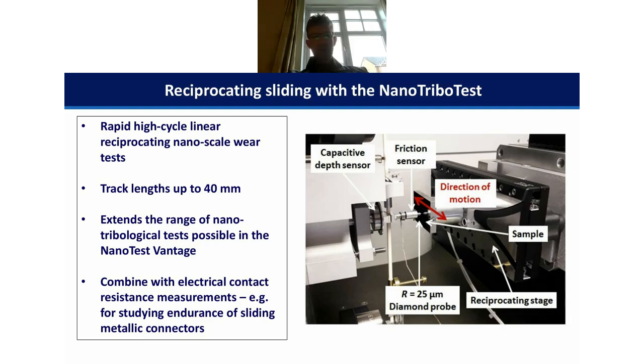So we've looked a little bit further at these sliding contacts with our new NanoTribo test. Here we have an additional stage, which we control within the NanoTest software. And it rapidly goes backwards and forwards here. This allows us to perform very high cycle tests, very long track sliding distances, and we can even combine with electrical contact resistance measurements.